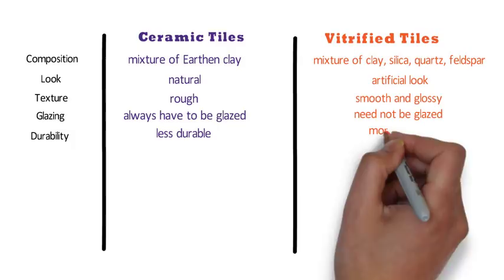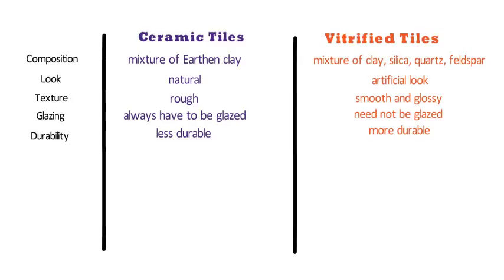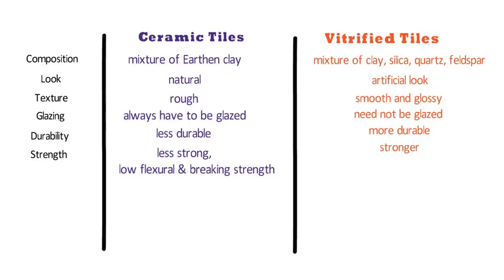Number six is strength. Ceramic tiles are less strong than vitrified tiles. Ceramic tiles have low flexural strength of 22 Newton per mm² and low breaking strength of 200 Newton. Whereas vitrified tiles have high flexural strength of 35 Newton per mm² and high breaking strength of 700 Newton.